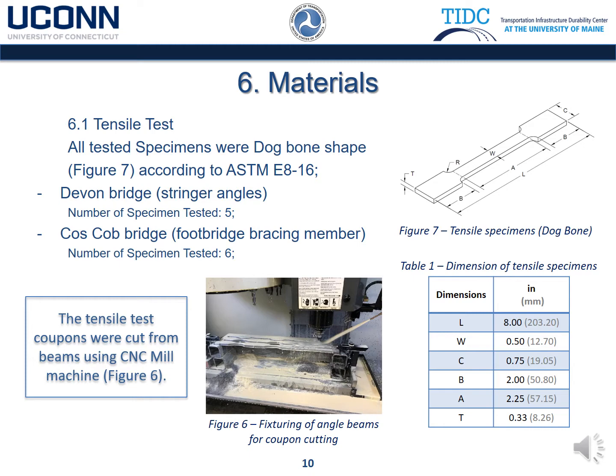Materials. All the tensile specimens were milled from sampled material of the selected bridges. Figure 6 shows an example of specimen preparation using the CNC milling machine. The specimens are in dog bone shape according to the ASTM E8 specification. Figure 7 and Table 1 show the geometry and the dimensions respectively. For this presentation, a total of 5 specimens for Devon Bridge and 6 specimens for Cos Cob Bridge were tested.